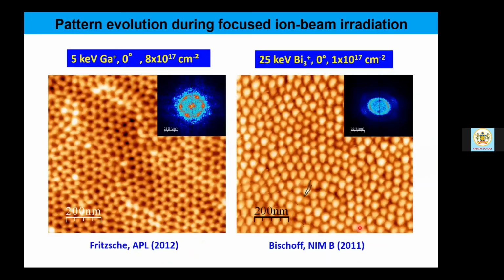And this is the case of germanium. So in one case, gallium ions were utilized. In another case, bismuth cluster ions were utilized. And on germanium, beautiful facets were formed. And here honeycomb structures are seen very easily. And the fluence was not very high when compared to the fluences that we have talked about mostly.